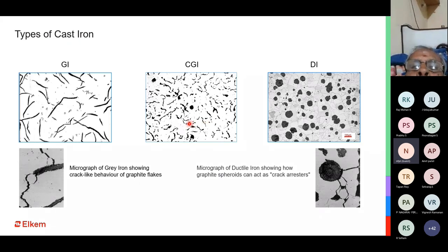And thereby, what does it do? It gives you a strength which is higher than gray iron, and it gives you a conductivity which is better than gray iron. So all three kinds of iron do find application, depending upon the type of casting that we are making and the type of requirement that we have from that particular casting.